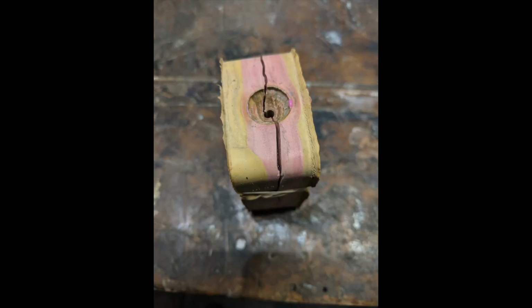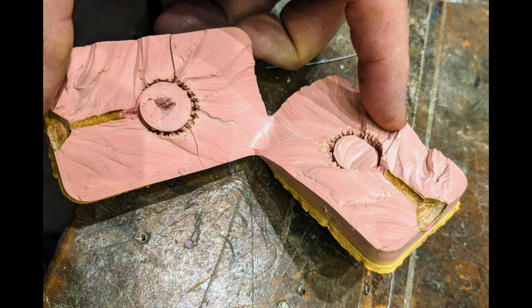So I made this sandwich mold with the gold on the outside and the pink rubber on the inside. I spent a lot of time working out the temperature of the pink mold so I got minimal shrinkage. Once the mold was vulcanized at approximately 310 degrees at 7.5 minutes per layer, I then cut open the mold and I got a very nice copy of her ring out of the vulcanized rubber that she could also use in the future.